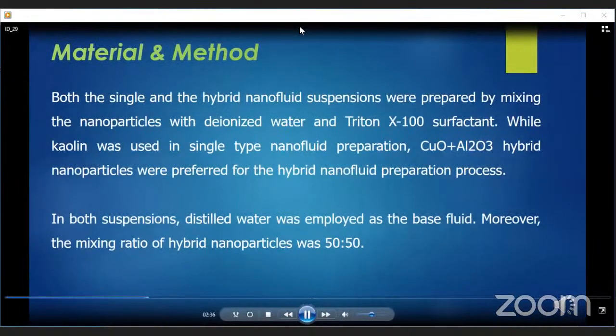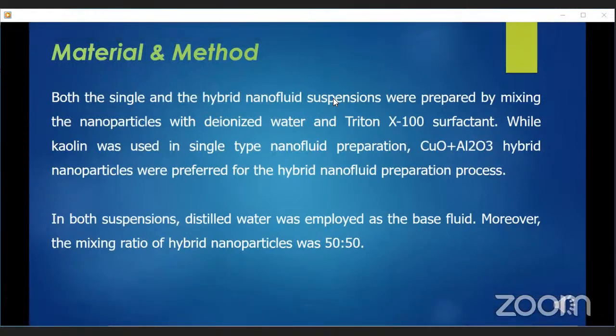Both the single and the hybrid nanofluid suspensions were prepared by mixing the nanoparticles with deionized water and Triton X100 surfactant. While kaolin was used in single-type nanofluid preparation, copper oxide and alumina hybrid nanoparticles were preferred for the hybrid nanofluid preparation process. In both suspensions, distilled water was employed as the base fluid. Furthermore, the mixing ratio of hybrid nanoparticles was constant at 50-50.